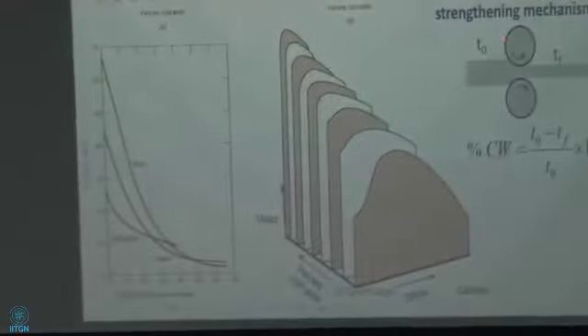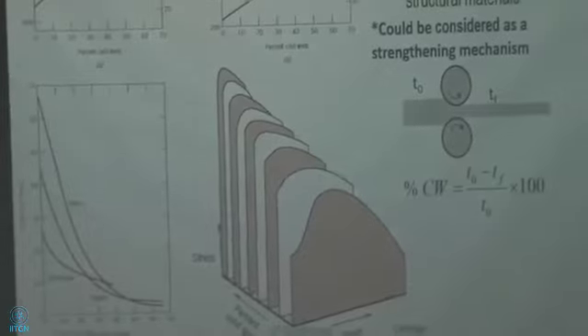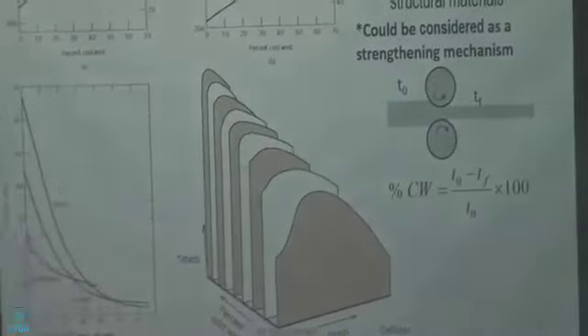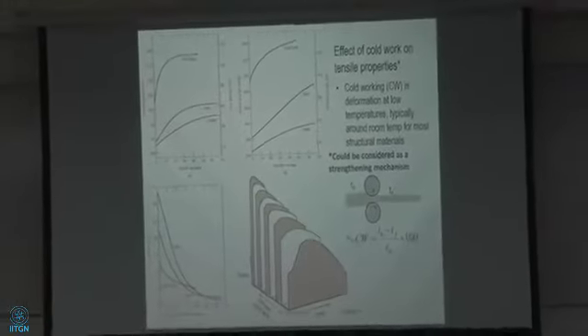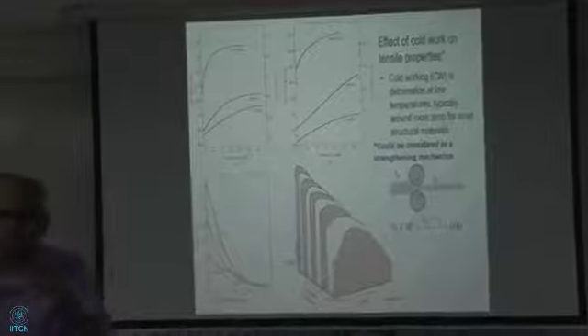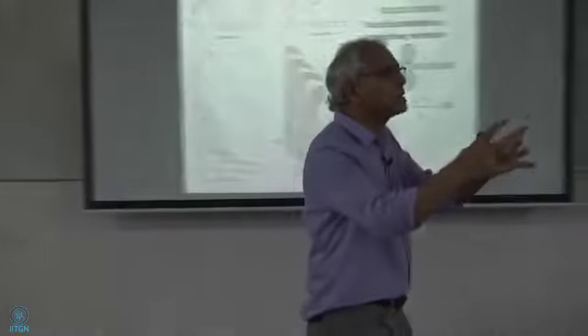So you can put cold work. One important thing I want to tell you, you can put cold work using the rolling process, or you can use a tensile machine. If I take a blank piece of aluminum, solution heat treated, it's very soft. And I put it through a rolling mill and put 20% cold work on it. What I'm doing in terms of dislocations is increasing the dislocation density by putting in cold work, right? I can do tensile deformation, or I can put it through the rolling mill, and I'm putting in dislocations.